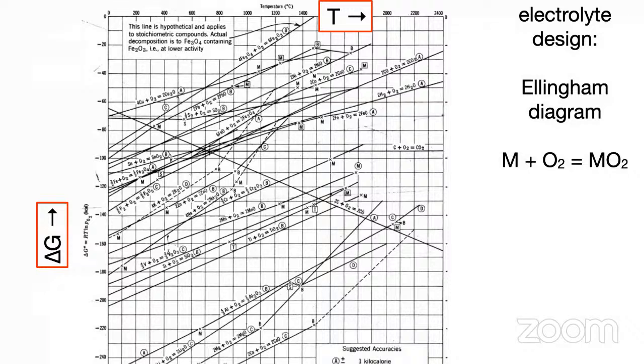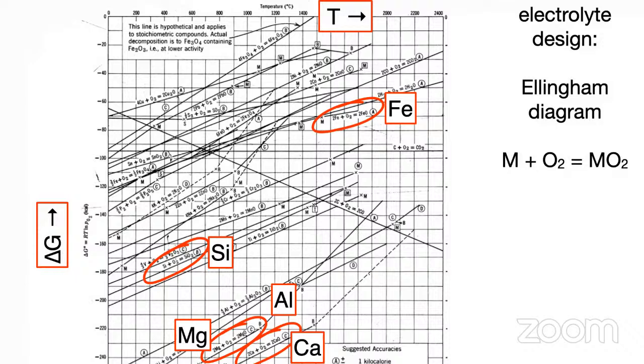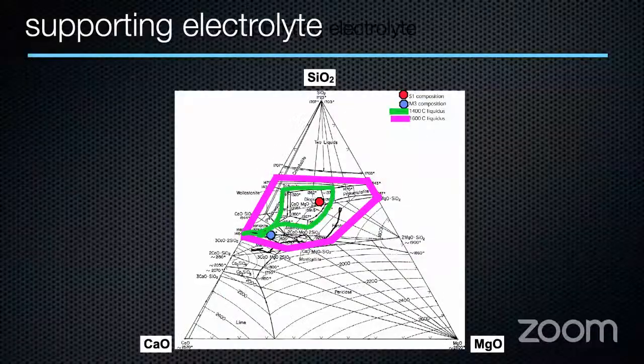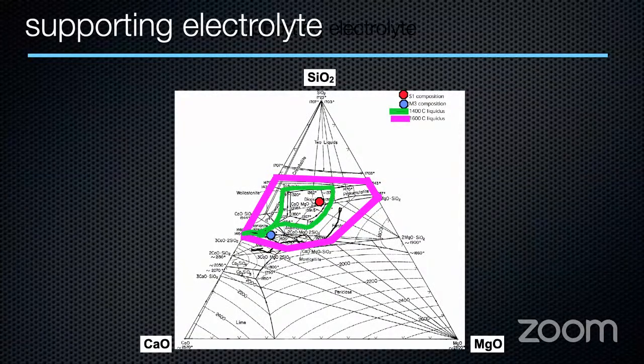So the electrolyte design, we started with the Ellingham diagram. Stable oxides are at the bottom, the unstable ones are at the top. Iron is somewhere in the middle, maybe towards the top. Anything below iron will not deposit in favor of iron. So our supporting electrolyte or solvent could be silica, could be alumina, could be calcium, whatever. But this is sort of the way we started. You know, add some magnesia if you want. Then we go to ternary phase diagrams, and the purple area gives you where you've got the boundaries. You've got to be somewhere inside that zone, otherwise the electrolyte will freeze up on you. So this is sort of the basics of electrolyte design.